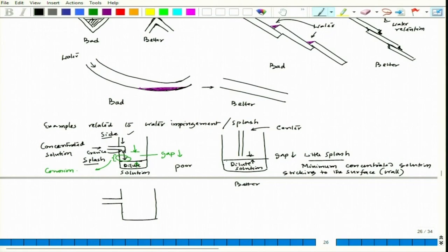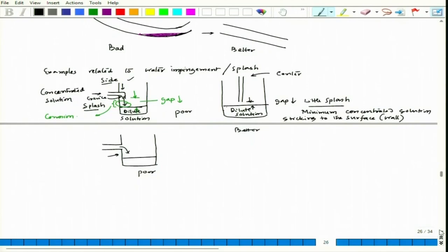tank. But if the dilute solution layer is here and the gap between the exit point of that inlet pipe and the dilute solution layer is high, again splash can happen, and that splash will be closer to the wall of the tank. So, that can lead to another severe problem, because a lot of solution can stick to the surface of this particular wall, and corrosion can happen. So, you are avoiding crevice, but you are actually bringing in another problem of splash, more splash. So, this is also poor. Okay. So, that way one can actually avoid impingement as well as splash in a situation like this.